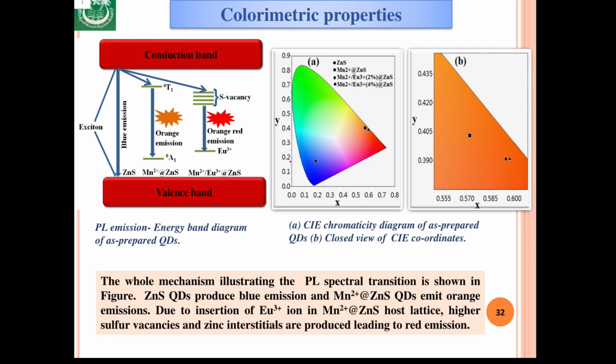Incorporation of the europium 3 plus ion in the zinc sulfide lattice leads to the presence of sulfur vacancies, and thereby we find that it is possible to have orange red emission from these doped zinc sulfide quantum dots. We can see from this CIE diagram plotted for the PL emission that this pure or undoped zinc sulfide